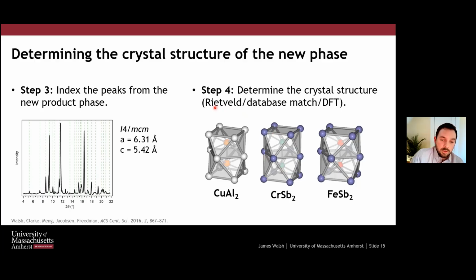But you could also, in theory, do Rietveld. I think that's a bit more tricky. I don't think you really would get the quality of data that you need to do a Rietveld solution of a phase, but you can at least do refinement if you can get to the phase another way. As I said, what we do was really using databases to match. We could also use DFT, and I'll come back to this and mention this later on. We could use those crystal prediction approaches to try to get the answer.